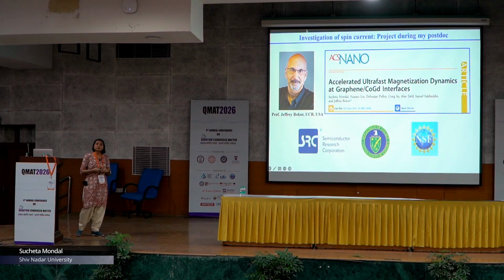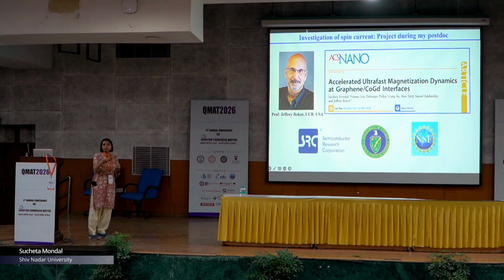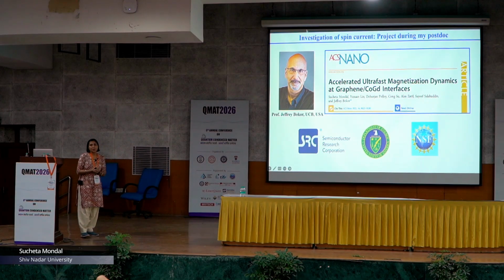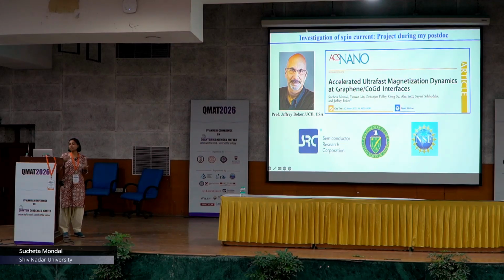Later part of time I moved to Berkeley for my postdoc with Professor Jeffrey Bokor, and there I got an opportunity to combine my work with 2D material. So, we studied ferrimagnet and graphene interface. There we optically generated spin current at the interface, and not only the precessional dynamics, I will explain what is that, also the ultra-fast demagnetization and remagnetization got affected by the hybridization between two interfaces.